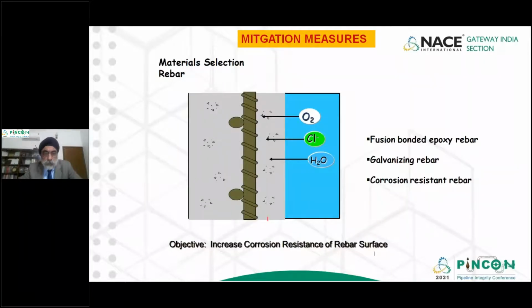Material selection. We can have a normal rebar. We can have a corrosion-resistant rebar. We can have a fusion-bonded epoxy rebar. We can have a galvanized rebar. Mostly for buried structures, fusion-bonded epoxy rebars are used. Galvanized rebars are normally used for atmospheric conditions. Corrosion-resistant rebars are also not used for buried applications. They are normally used for above-ground applications.